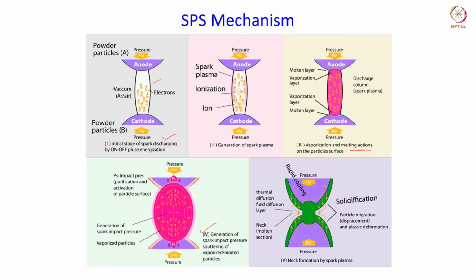And at the contact points, there is also rapid cooling, as we talked about before. And there is thermal diffusion also, due to the intense heating and the temperature gradient that you may have from the contact point towards the core of the particle. So this leads to material transport towards the neck. And here there is localized melting also because of the intense localized heating. And that is again good for the diffusion process at this neck. And when it is cooled down, this molten material will ultimately solidify, and as the pressure is applied, plastic deformation will happen and the densification will occur by plastic flow. Okay, so these are the different kind of phenomena which occur during the SPS process.